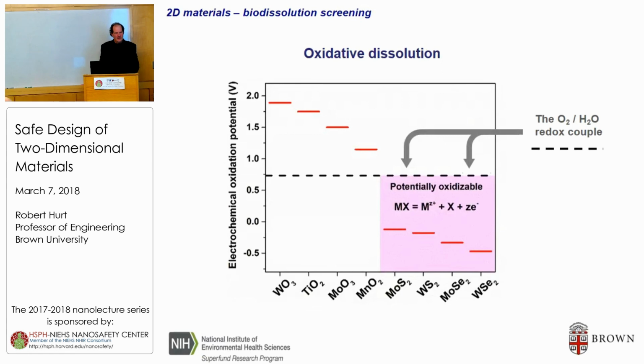Molybdenum disulfide, when it oxidizes, usually oxidizes from the edge or at defect sites that widen. It doesn't oxidize through the thickness, as you can imagine. So it's probably edge-mediated. And for the small lateral dimension, the shorter the distance you have to go through to slowly oxidize and dissolve the material, one could imagine that the overall fineness would be an important variable, and there could also be shape-dependent effects, as was mentioned by a previous questioner, but we don't have data on these things. Certainly size is important for dissolution kinetics, most certainly.